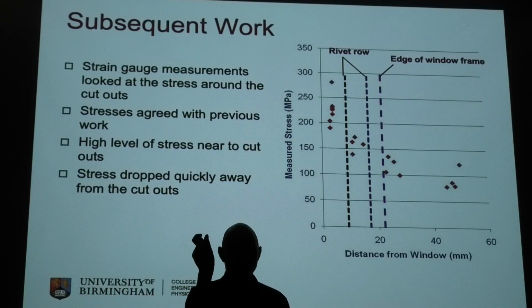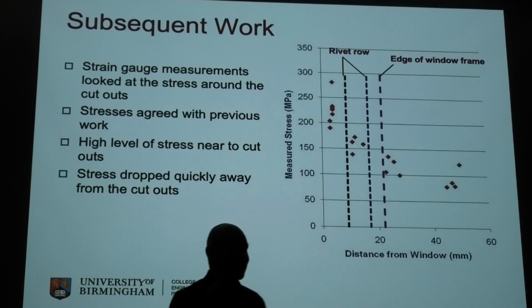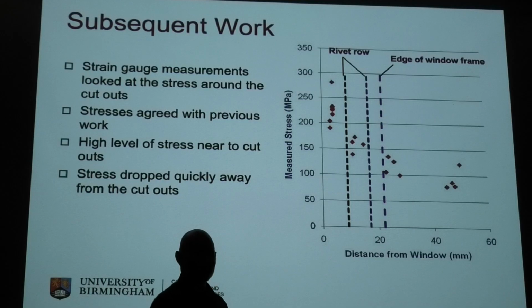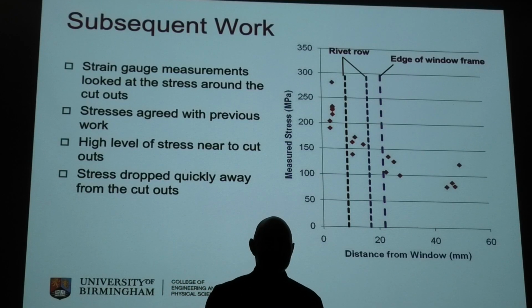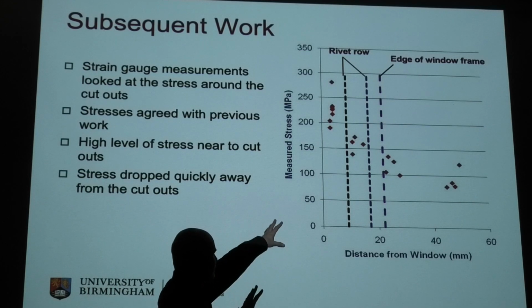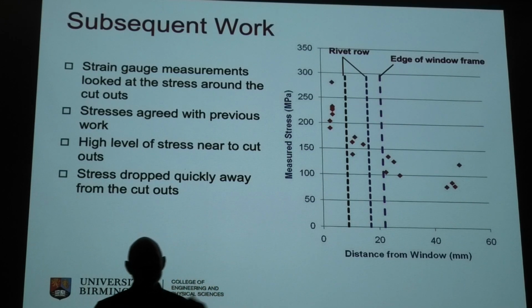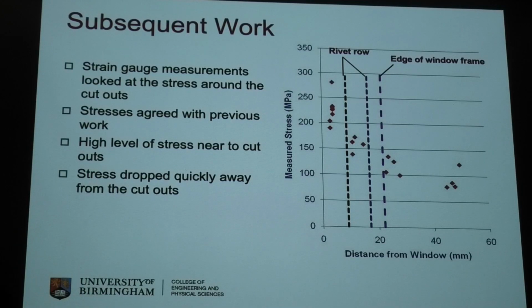because the window's a big stopper hole, or they grew out to the second row of rivets and stopped, and so the only fatal cracks grew out from the second row of rivets into the rest of the airframe. So actually from a much lower stressed region, we're down in about 100, 125 megapascals at that point. And so actually, interestingly, the fatal cracks weren't in the high stress field anyway.